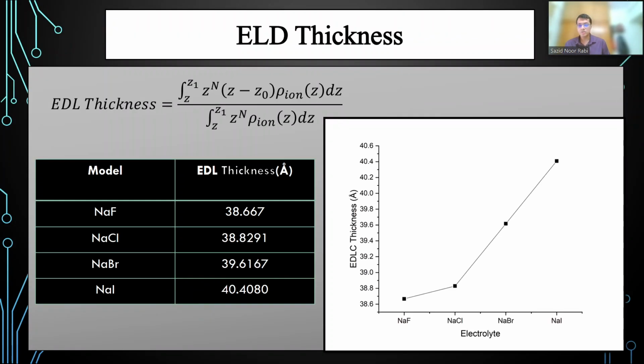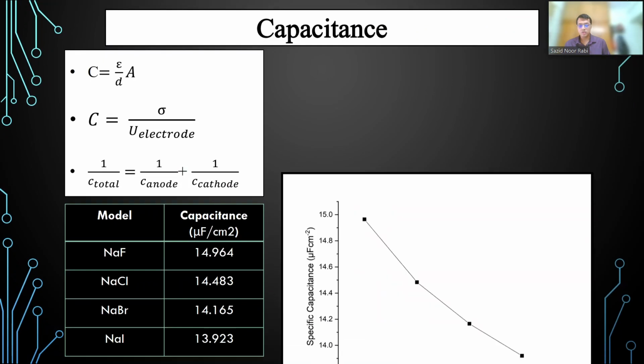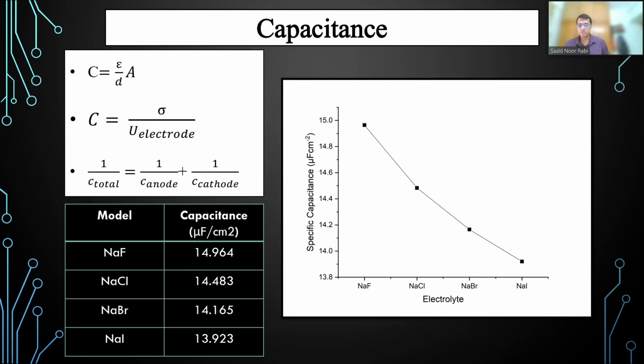Here we have used this formula to find the EDL thickness of our model. We can see that sodium fluoride has the lowest thickness while sodium iodide has the highest one. In case of capacitance, however, there is the opposite effect. Sodium fluoride has the highest capacitance and sodium iodide has the lowest capacitance.